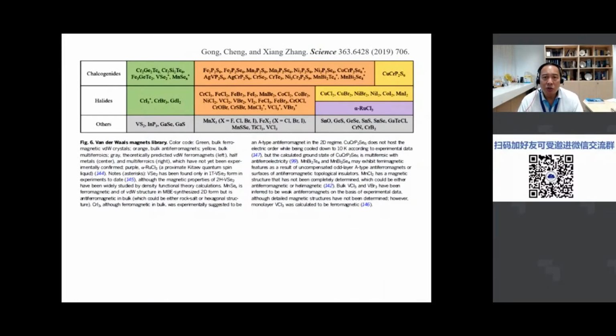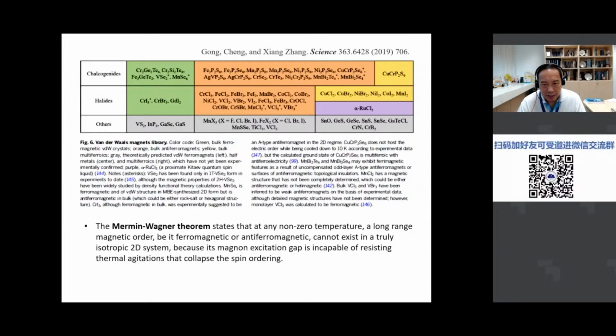Okay, and then Xiang Zhang also wrote a review in Science that summarizes all the possible van der Waals magnets that we have. So this is the van der Waals magnets library. This is, of course, in 3D. And in green, you have those possible bulk ferromagnetic van der Waals crystals. In orange, you have the anti-ferromagnets and so on and so forth. But let's focus on the green ones, the ferromagnetic. And as mentioned, the Mermin-Wagner theorem states that at any non-zero temperature, the long-range order cannot truly exist. But you can create a magnon excitation gap capable of resisting thermal agitations if you introduce some anisotropy in the material.